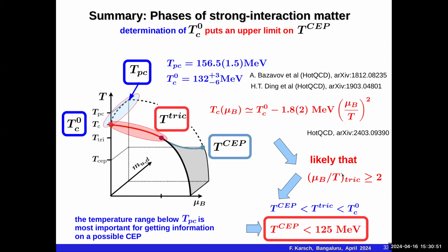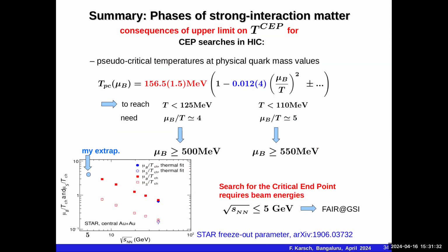So being conservative and saying that the tricritical temperature is to be found at a value of mu_B over T larger than 2, we already conclude that the critical endpoint temperature is most likely smaller than 125 MeV. So larger values of mu_B actually put it close to 100 MeV. But I think estimating it to be smaller than 125 MeV is a conservative estimate. And this has some drastic or relevant effects for searches of a critical endpoint in heavy ion experiments.